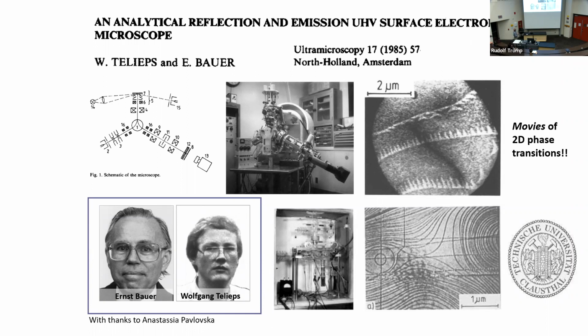showed a movie of this silicon 111 surface, where at high temperature, there's a coexistence between two phases, a disordered one, what we call the 1 by 1 phase. And these little triangles that come out of the atomic steps is the famous silicon 111 7 by 7 reconstruction. And there'd been a long discussion about whether this was a first order or a second order phase transition. Here you see coexistence of the two phases side by side. So there's no more question, it's a first order phase transition that stretches over some temperature range due to finite size effects. Right? And so I saw that movie and I was interested in epitaxial growth.